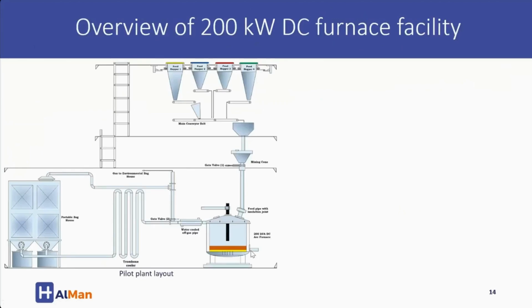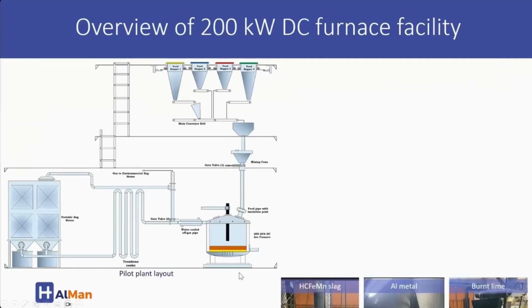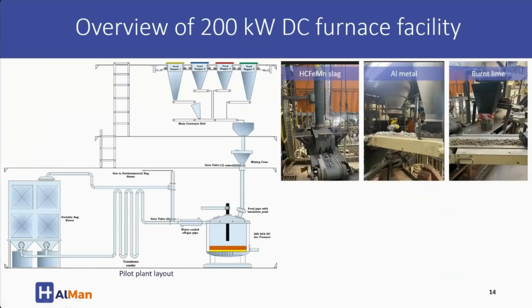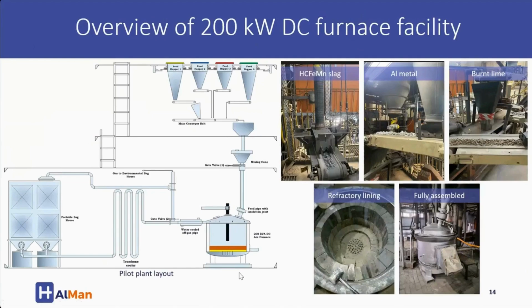So what facility did we use? We used MINTEK's 200 kilowatt DC furnace facility, which is remotely controlled and well facilitated with a feed system that is remotely controlled, as well as a circular furnace with a central graphite electrode, and a dedicated off-gas handling system. These are pictures showing the actual facility, and as you can see, the furnace was refractory lined with, I believe, 96% MgO bricks.